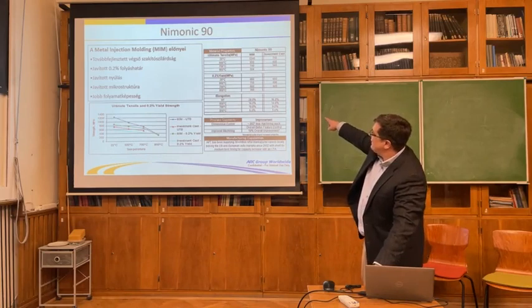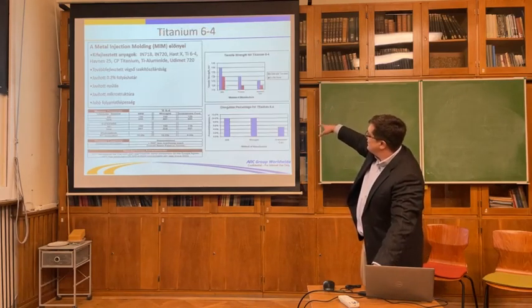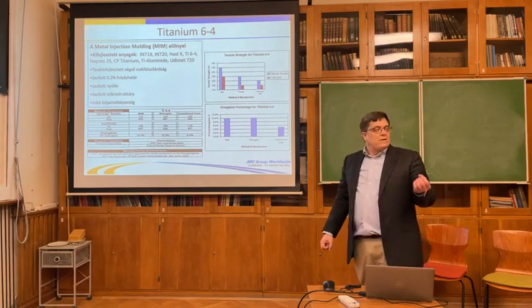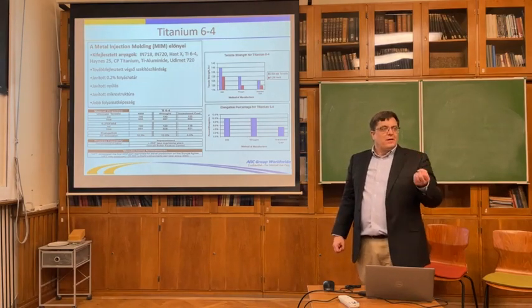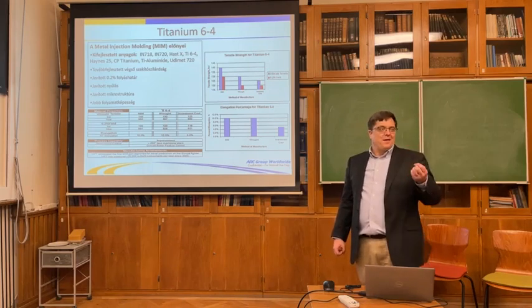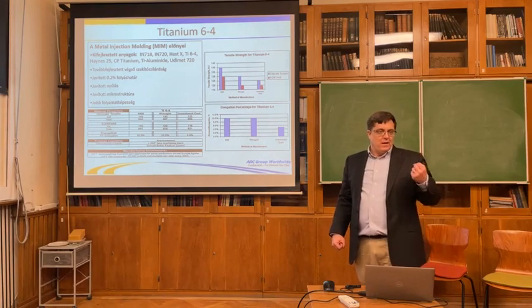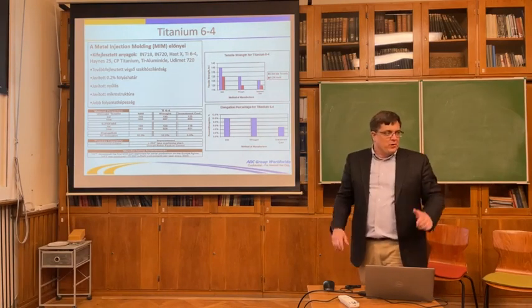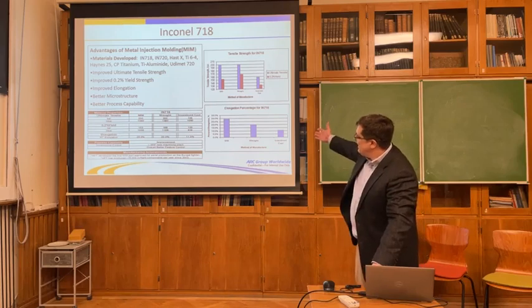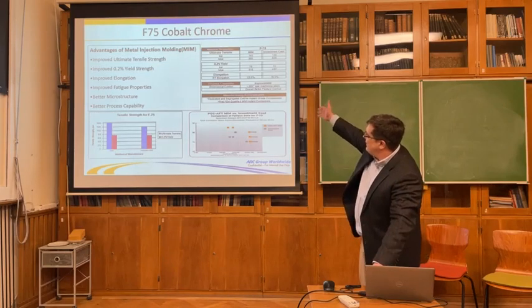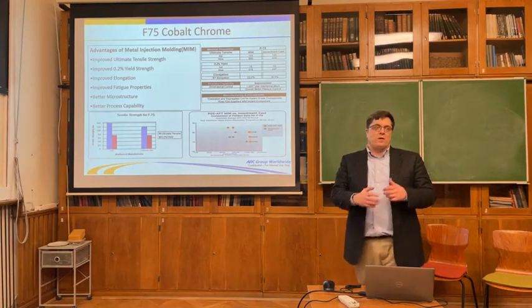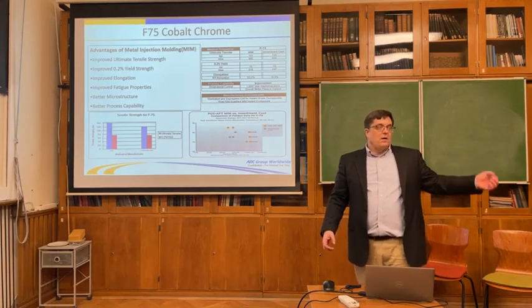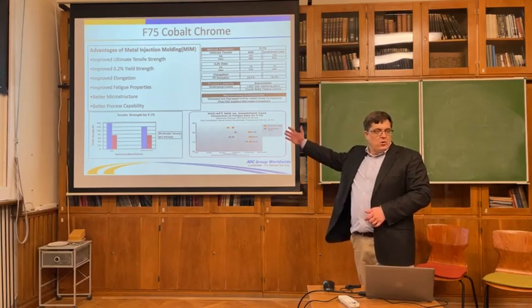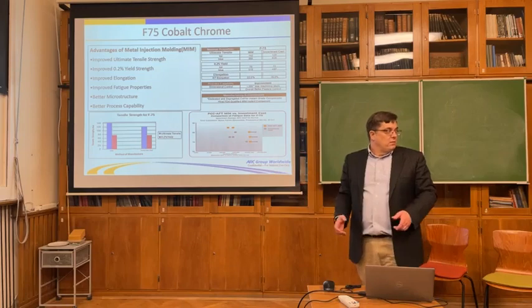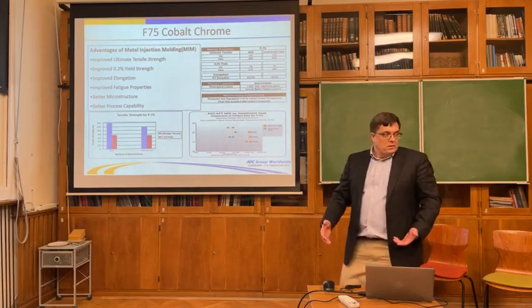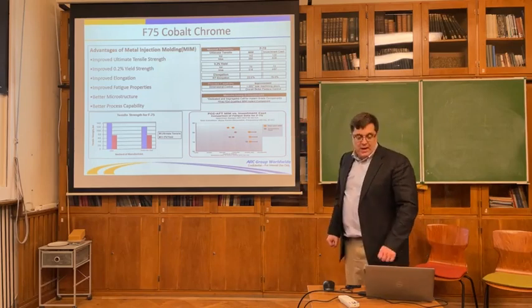So the same thing happens here with Nimonic 90. That's another high exotic material. Titanium 6-4. Really difficult to mold, because if you guys ever work that stuff, it's expensive, and it's an oxygen grabber. You have to have something taking out the oxygen, otherwise it's brittle. Inconel 718, another big one with nickel. Then the F75 cobalt chrome is used for implants. You can use titanium, very difficult. But if you can't use that, you can use cobalt chrome for implants, and they do some of that. Knee surgeries, as we all get older, knees, hips, that's the material that they make it out of.